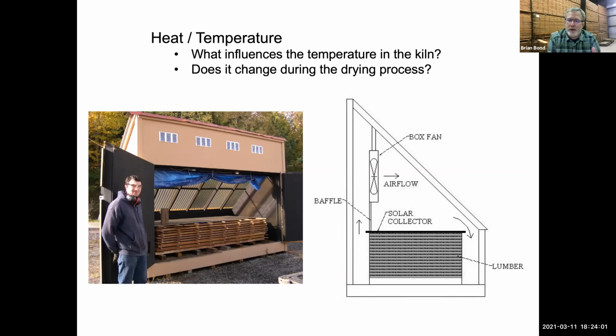Well, that's good, because as the drying process continues, we want the temperature to be higher, because that's going to help drive diffusion. What the heck is that? That is moving the moisture from the center of a piece of wood to the surface so that it can be evaporated. After a while, through the thickness of a piece, you've got to get that moisture to move through the center of that piece to the surface to get it evaporated. Well, one way to do that is to increase the heat. And so just how the process works, you will see the temperature increase as the drying process progresses naturally in the solar kiln, which is an advantage to us.